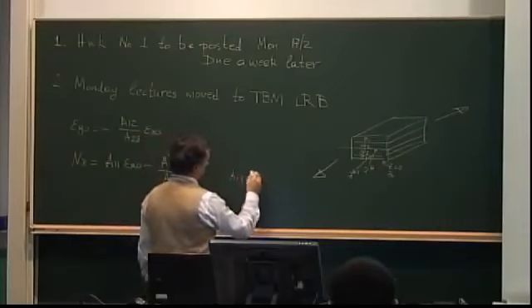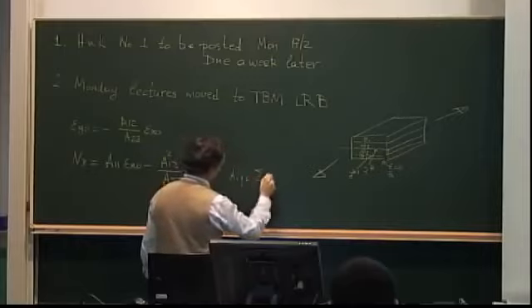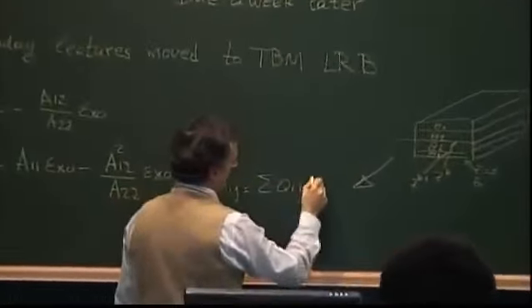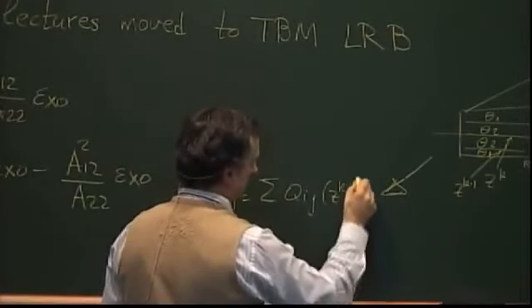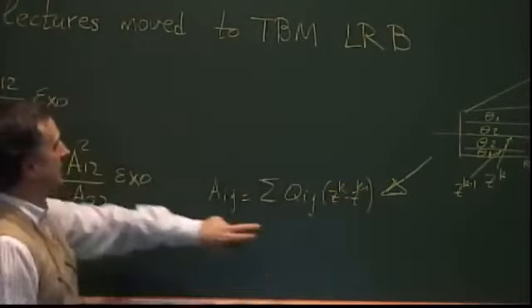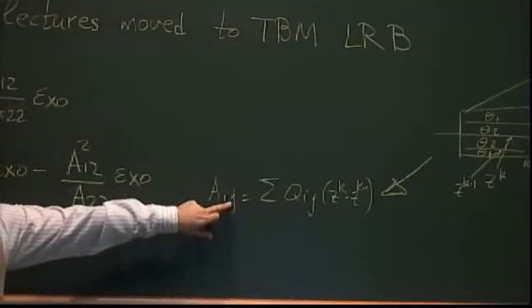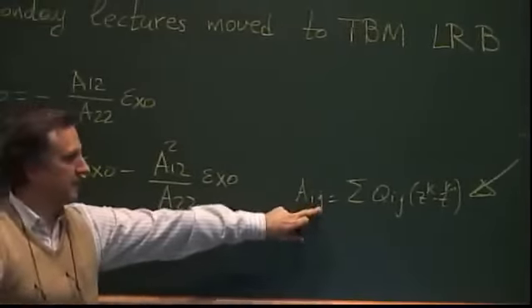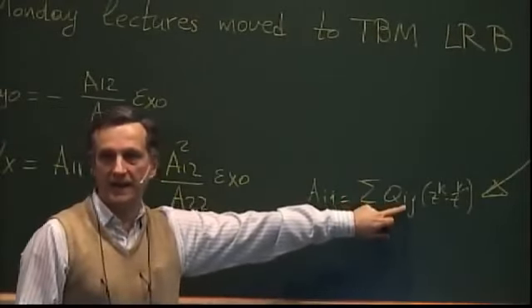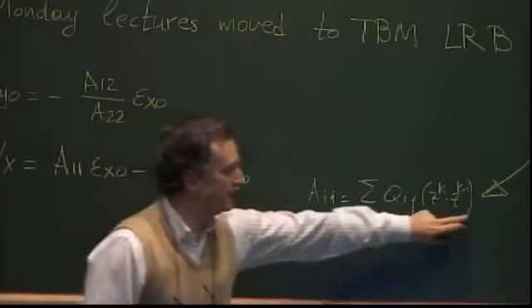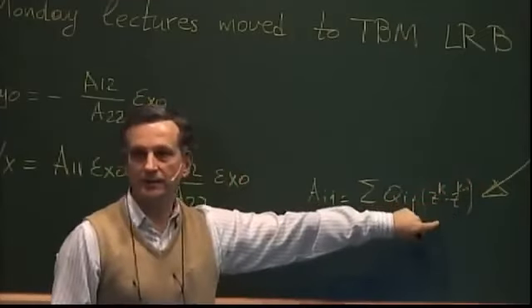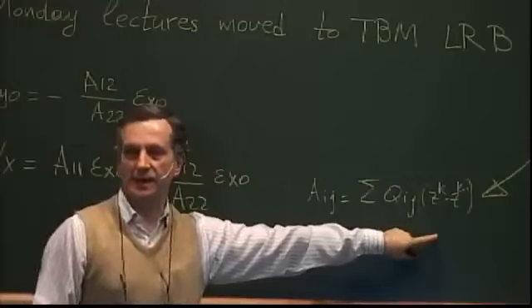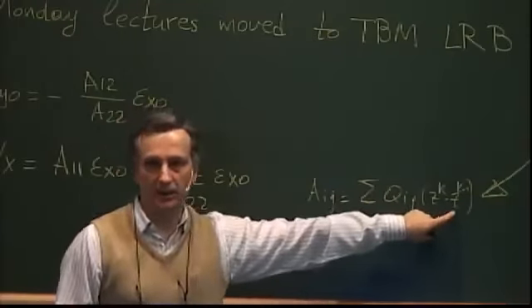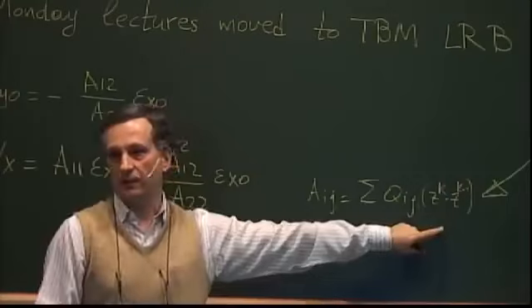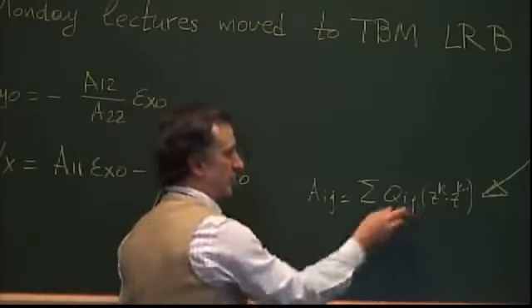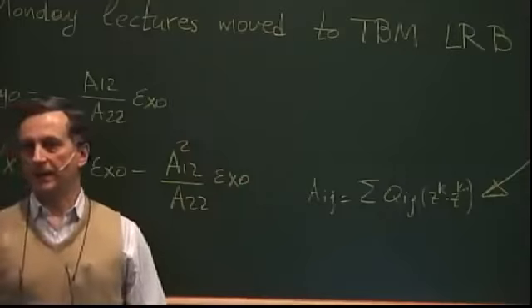Aij is summation of Qij times the Zk minus Zk minus 1 term, which means for a certain stiffness in a certain direction, let's say the 1-1 direction, you take the stiffness of each ply in that direction and multiply it by this. This now becomes a weighting factor. It so happens if all the plies have the same thickness, this term would be exactly the same, but not all the plies will have the same thickness in a general design if you use different materials. So there's a weighting factor, and this then makes it some kind of a weighted expression.